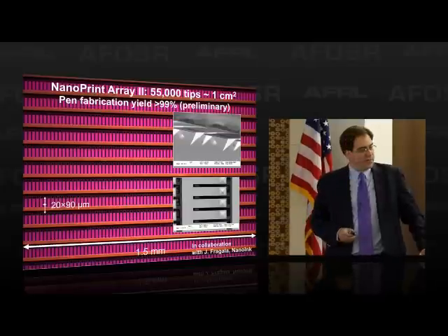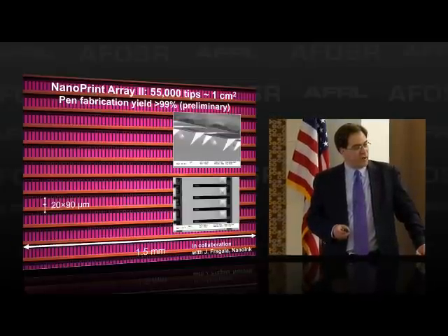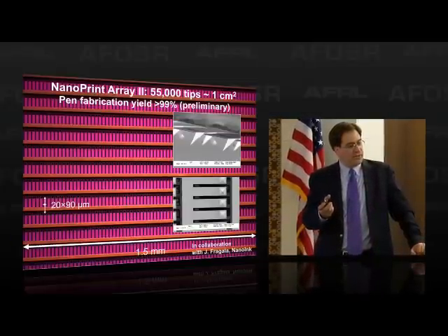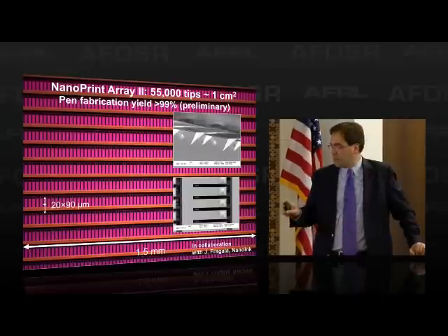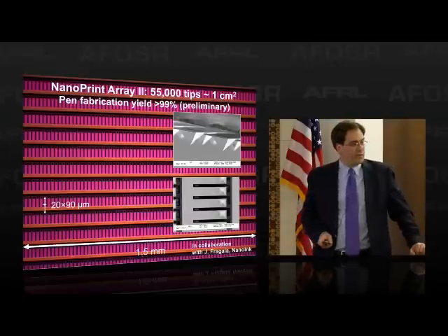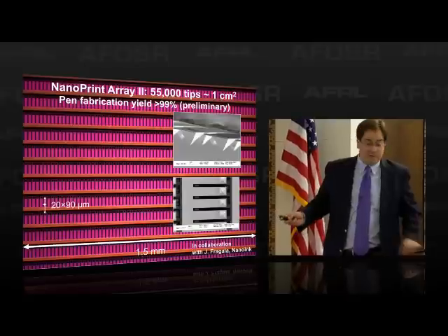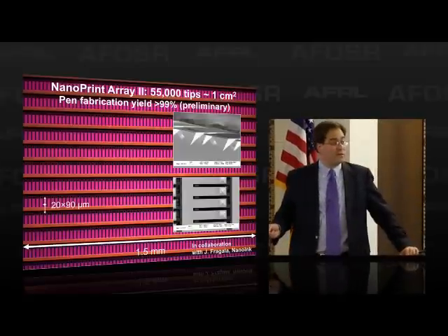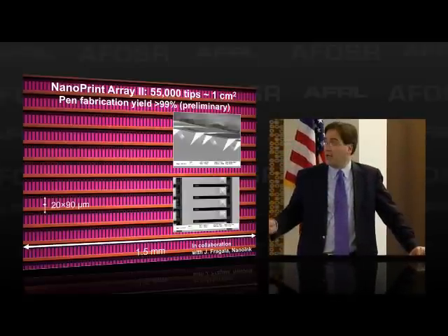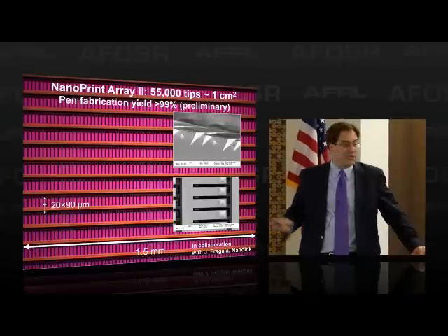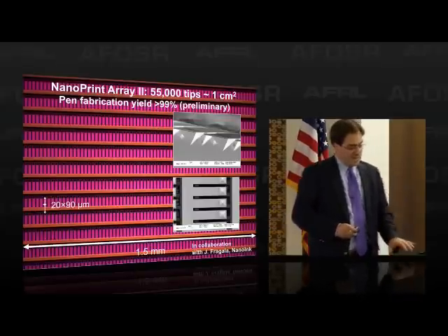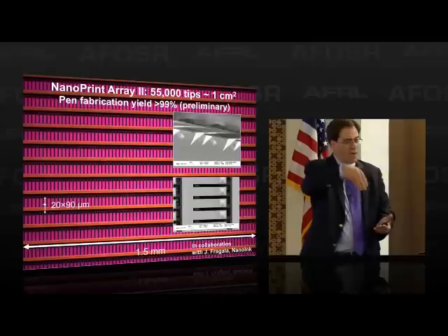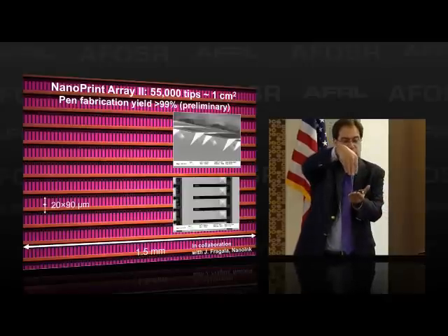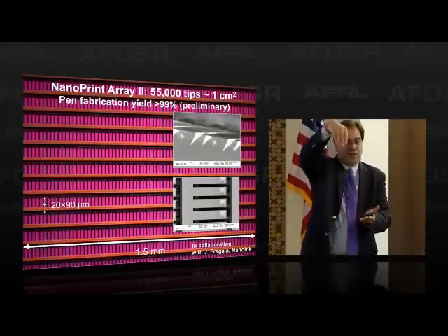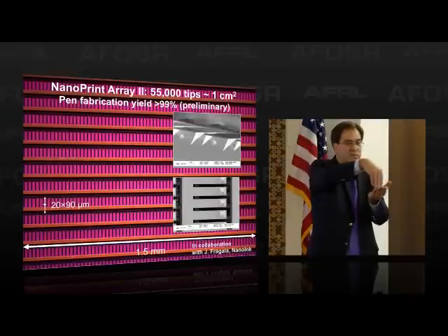Well, he said, because the feature size is independent of contact force, in principle we can make large arrays like the one shown here. This is the largest array ever made, or actually at the time it was the largest array ever made: 55,000 pens in a square centimeter. These are all AFM cantilevers, and you can see the high magnification image here with the tip. And here's the problem. When you have an array, whether it's linear, and it's really bad if it's two-dimensional, you can never get all the pens perfectly aligned in one plane. So one's going to hit first.